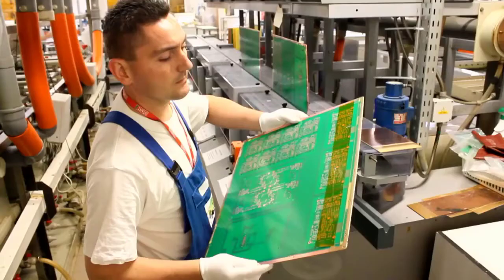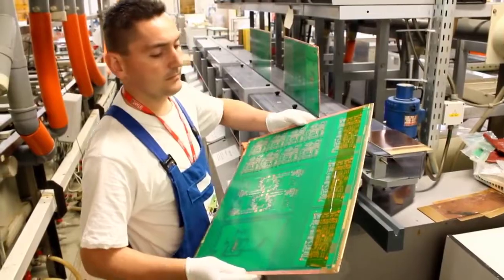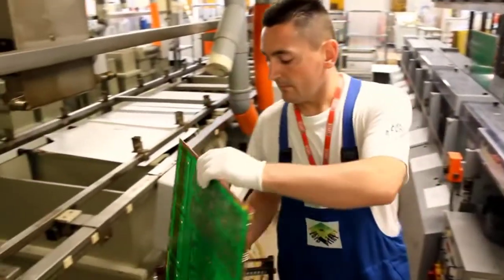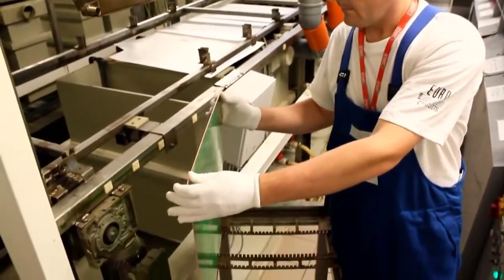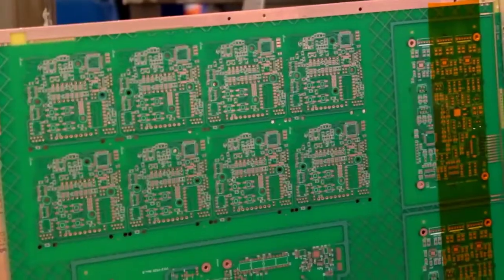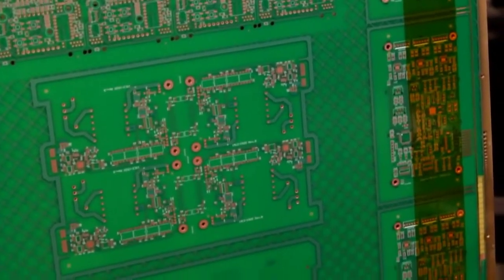For edge connectors, we electroplate 1 to 1.5 microns of gold over 4 to 5 microns of plated nickel. So if your PCB will be repeatedly inserted into a connector, you should specify hard gold plate on the edge connectors. When the edge connectors have been plated, we will remove the tape.